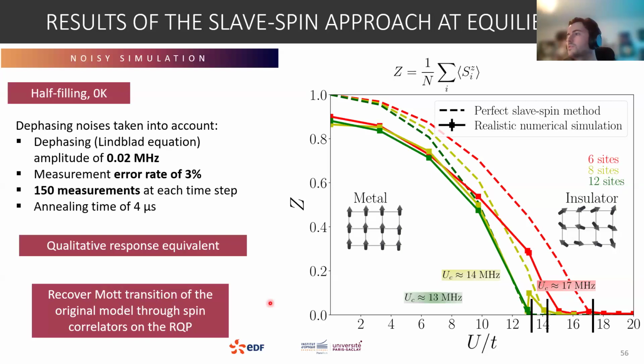So now, what if we take into account the noise inside the Rydberg quantum platform? Of course, we are in the NISQ era, and we have to take noise into account. For my numerical simulation, I used several types of noise. For instance, dephasing for the lasers which are controlling the atoms. Error rate in the measurement: it is possible to measure 1 instead of 0 and 0 instead of 1. Also, we only have access to a small number of measurements at the end of the annealing procedure. Of course, we do not have access to the full state vector because of the projection of the state. So I have bounded my measurements to 150 at each time step.